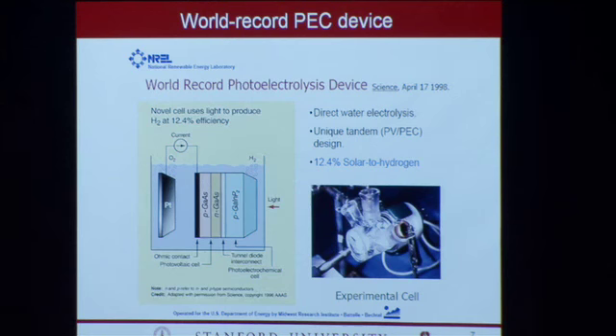And this is a device in which he took a gallium indium phosphide and deposited onto effectively a PN junction gallium arsenide solar cell. And the idea is when he shined light onto this device when immersed in water, he evolved hydrogen here on the gallium indium phosphide surface, he evolved oxygen off of the platinum surface, and he was able to achieve a 12.4% solar to hydrogen conversion rate. Okay, that's taking all the solar energy impinging onto that material. 12.4% of that energy actually came out as molecular H2.